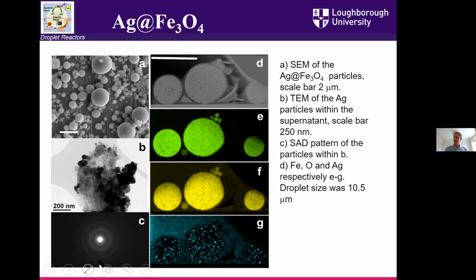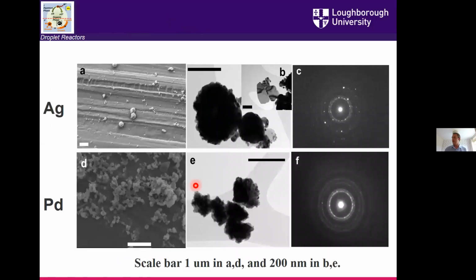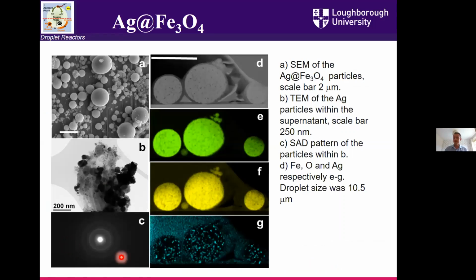And it's interesting to note that whereas before we had very nice diffraction patterns for the silver made in the absence of iron oxide, here we have something which is less crystalline in its nature on average. And so it tells us that they're different sizes and that the reaction process is a little different.